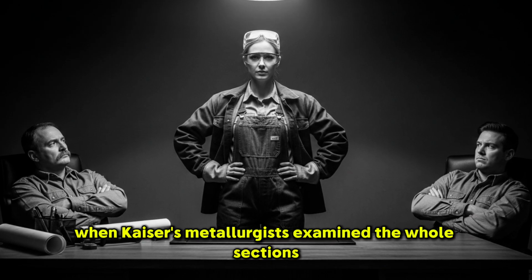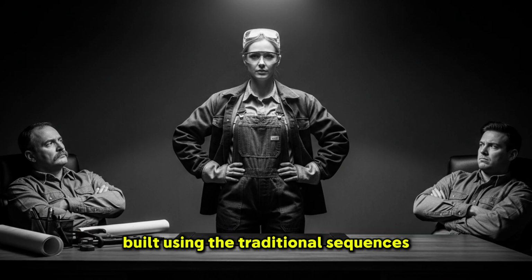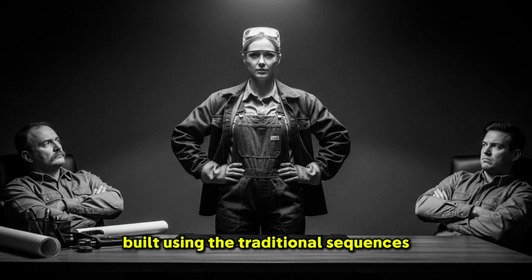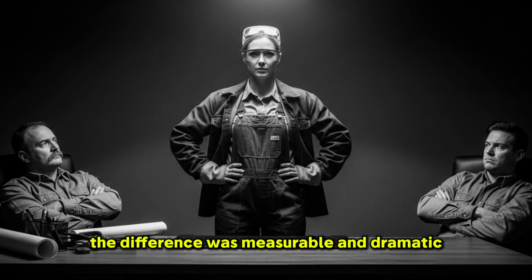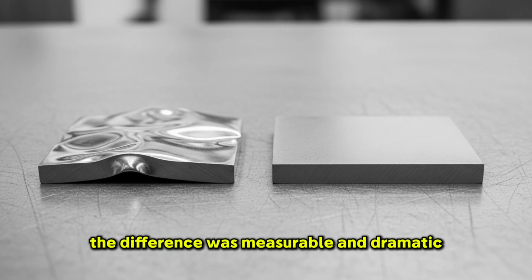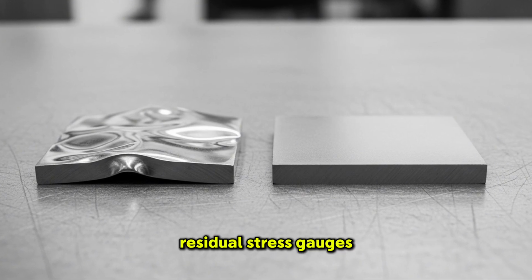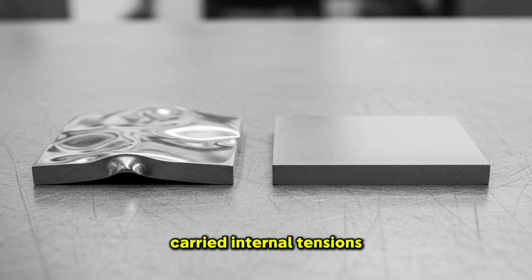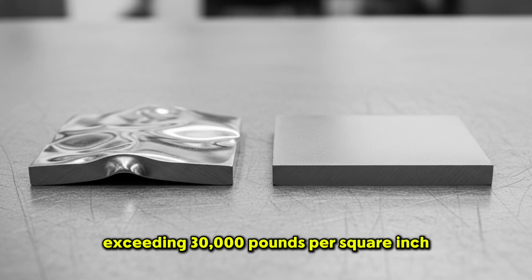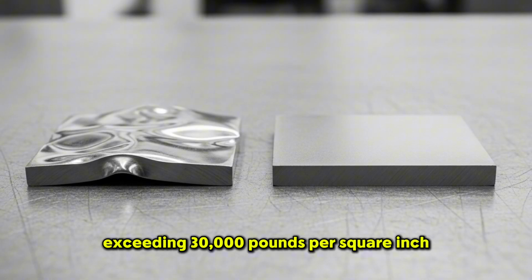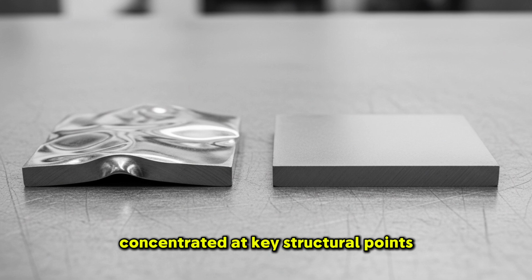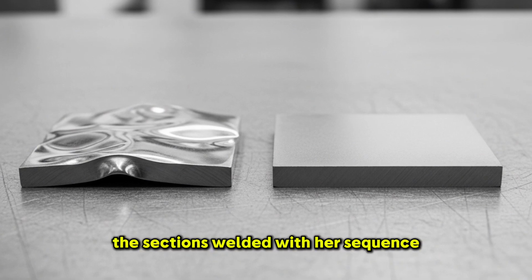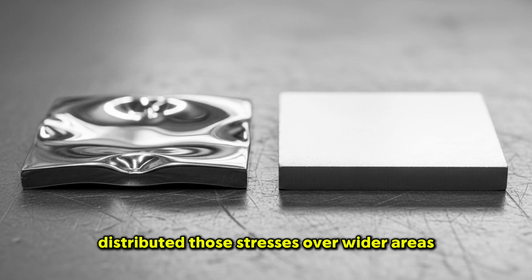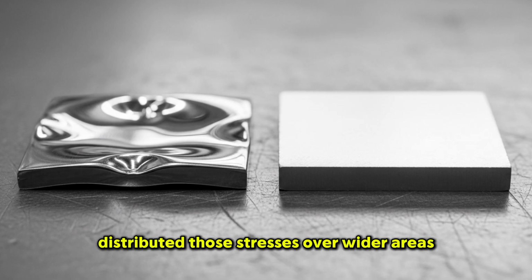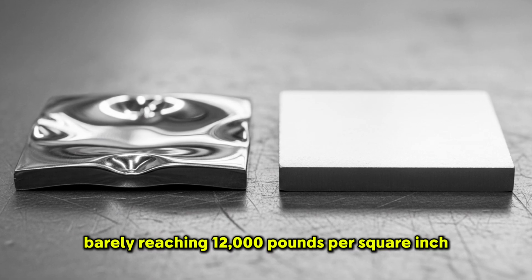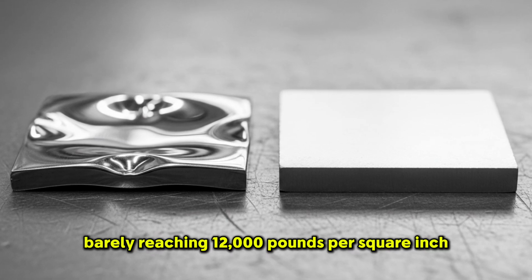When Kaiser's metallurgists examined the hull sections built using the traditional sequences versus the welder's methods, the difference was measurable and dramatic. Residual stress gauges showed that the traditional welds carried internal tensions exceeding 30,000 pounds per square inch, concentrated at key structural points. The sections welded with her sequence distributed those stresses over wider areas, with peak readings barely reaching 12,000 pounds per square inch.